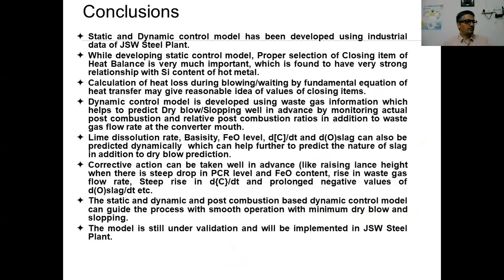Based upon the static and dynamic control models developed using the industrial data of the JSW Steel Plant: while developing the static control model, the proper selection of the closing item of the heat balance is very important. It was found to have a very strong relationship with the silicon content of the hot metal. Then the calculation of the heat loss during blowing by the fundamental equation of heat transfer may give a reasonable idea about various closing items. Subsequently, a dynamic control model was developed using waste gas information, which helps to predict dry blow and slopping well in advance by monitoring actual post-combustion and relative post-combustion ratios, waste gas flow rate at the converter mouth, lime dissolution rate, basicity, FeO level, and decarbonization rate. Then the oxygen in the slag can also be predicted dynamically, which can help further to predict the nature of the slag in addition to dry blow prediction.